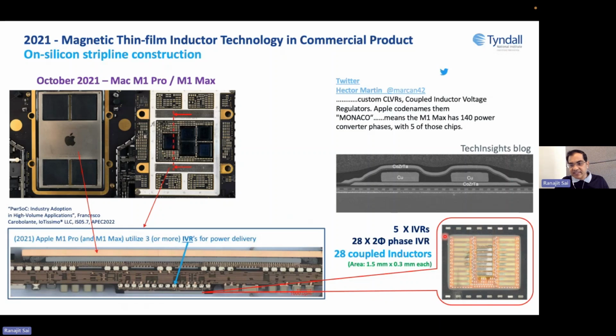And if you cut it top to bottom in one corner, then you will see this image, which has the PMIC underneath in some layers. Above that PMIC, there is a bottom magnetic layer, then 2 copper layers and a top magnetic layer, which is a classic coupled inductor structure. The top and bottom magnetic layers are cobalt, zirconium, tantalum based magnetic material. This is marvelous, because you can see there are very tiny 28 coupled inductors within one PMIC, and with 5 PMICs, that is a total of 140 power converter phases.